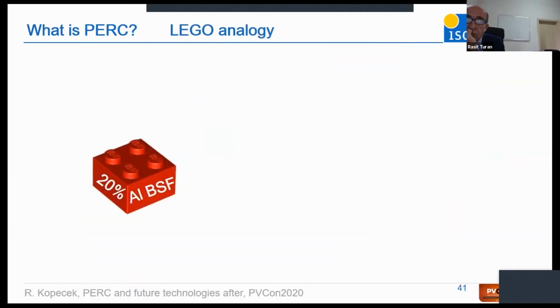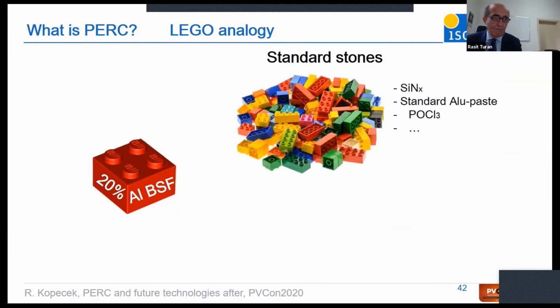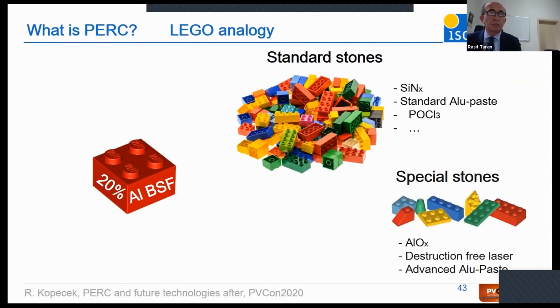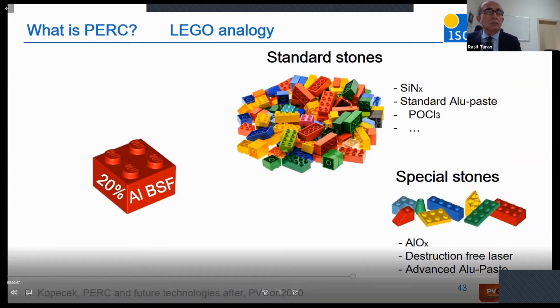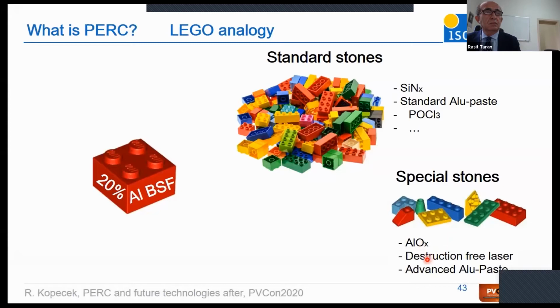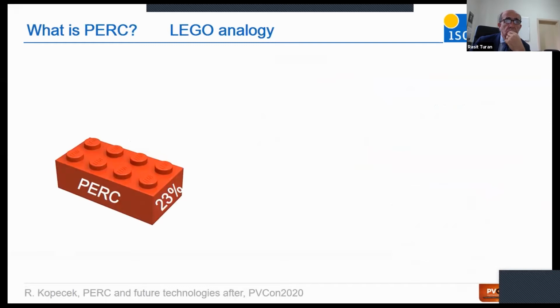But let me explain it in a different way with the Lego analogy. Everybody likes playing, everybody likes Lego, and at the beginning we had a very simple aluminum back surface field stone with 20% efficiency, and going to upgrades, you have, let's say, standard stones, and much more expensive and complex special stones. And at that time, when going to PERC, it was not clear how aluminum oxide can be used, how it is deposited, or destruction-free lasers, in which pulse the lasers have to work, and also the aluminum paste, which was not quite easy to develop for this purpose. But then it worked, and so at the moment we have a very nice and powerful PERC Lego stone with an efficiency limit of 23%.